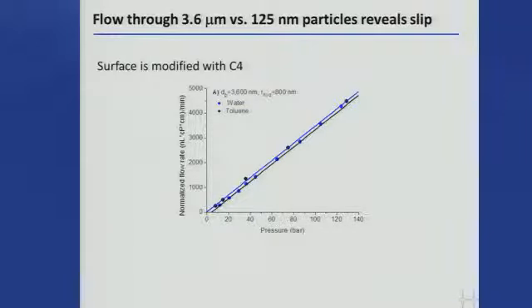So we played around with this a little bit to help illustrate slip flow, especially to the chromatographic community that wasn't familiar with it. And the reason they weren't familiar with it is it's a nanofluidic phenomenon, and so I want to talk about that a little bit. Why is it nanoscale and not microscale? And so if I take 3.6 micron particles, which would be very familiar to chromatographers, and plot the normalized flow rate for water and toluene, they line up